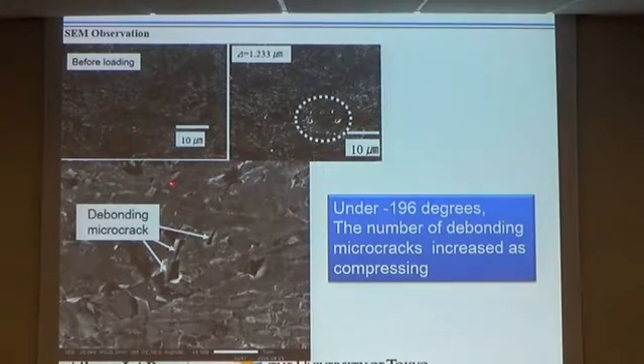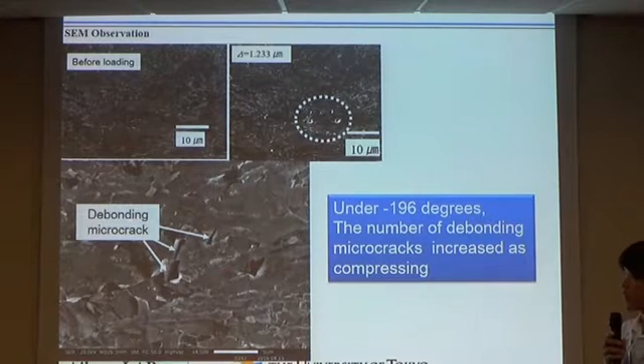This figure shows the in situ observation by SEM. Before loading, there are no microcracks, of course, but after loading, there are many microcracks, and the number of microcracks increased with the level of compression, and many of the microcracks were debonding microcracks between MA and the bainitic ferrite.